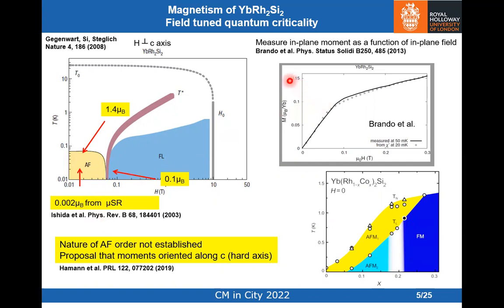Then there's another important measurement, which also hasn't received an awful lot of attention, I think: if you tune the field in plane, what happens? You develop an in-plane moment that grows linearly with in-plane field to a value of about 0.1 μB at the quantum critical field. So over here, you go into a Fermi liquid state. The moment here is 0.1 μB.